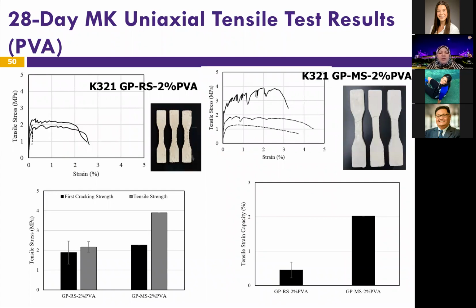So the first thing is we were able to successfully produce the ECC mixes. We got pseudo-strain hardening behavior, as you can see in these. So this figure shows the results of the 28-day metakaolin uniaxial tensile strength test. The specimen with the microsilica sand, right? You can see this one is a microsilica sand, presented the best tensile behavior by exhibiting a greater tensile strength and tensile strain capacity, but the river sand still worked, so they both can be used.